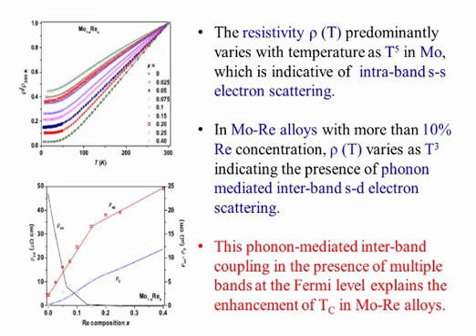The resistivity predominantly varies with temperature as T to the power 5 in molybdenum and in molybdenum-rhenium alloys with low rhenium concentration. With increasing rhenium concentration, this behavior changes gradually to a T cube variation. This indicates a changeover from an intraband s-s electron scattering in molybdenum to a phonon-assisted interband s-d electron scattering in the molybdenum-rhenium alloys.